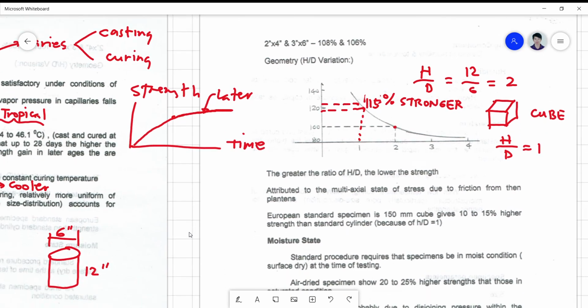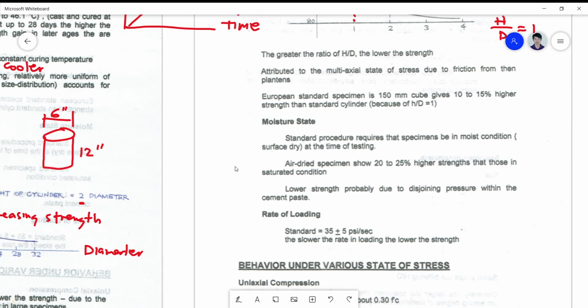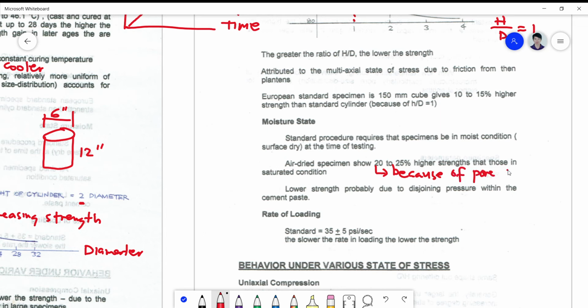Okay, moisture state. So standard procedure requires that the specimen be in the moist condition, surface dry at the time of testing. When you say moist condition, it must be surface dry, but inside the specimen there's moisture. Air dried specimens show 20 to 25% higher strength than those in saturated condition. This is because of the pore pressure buildup, no? So there's water pressure on this. Kaya nagkakaroon ka ng higher strength. Pag air dry, so lower strength probably due to the disjoining pressure within the cement paste.